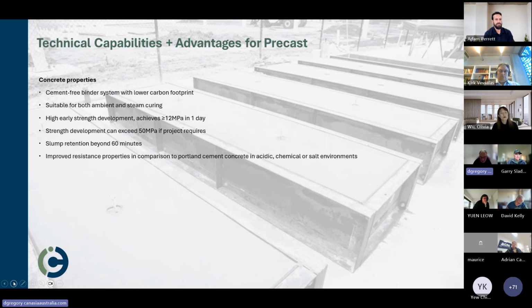Strength development is not an issue for us if the project requires. And we can demonstrate slump retention beyond 60 minutes if required. We can also shorten that to 15 minutes or less if required. It's a very, very adaptable system. And we are proving in collaboration with Sydney University, as part of this same CRC Smart Crete, that we offer improved resistance properties to acidity, to chemical and salt attack. So there are obvious market opportunities for those results.